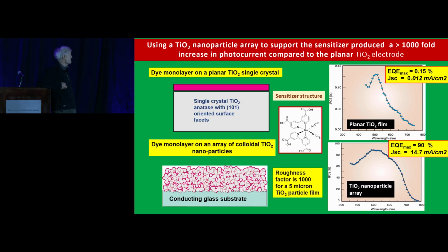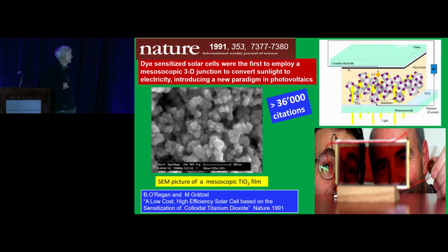And so, I won't go into physics. I don't have time, as to why it's possible to collect the electrons. Suffice it to say that the carrier diffusion length, the length the carrier can diffuse in those films before they recombine with the positive charge, is several hundred micrometers. And so that's much more than the film thickness, and so we could collect those carriers.